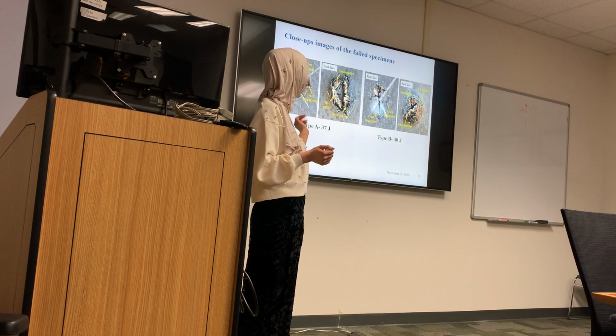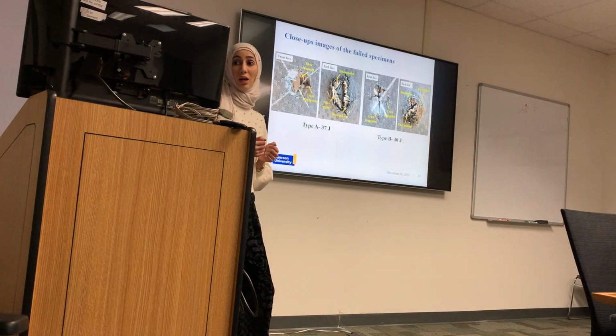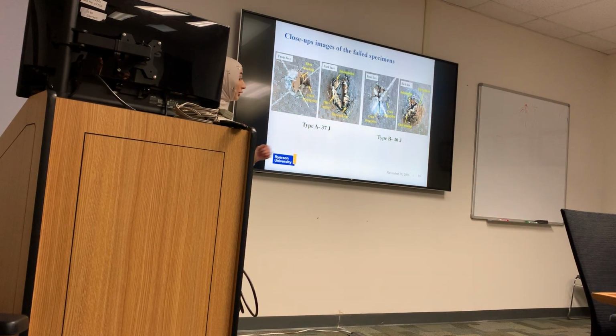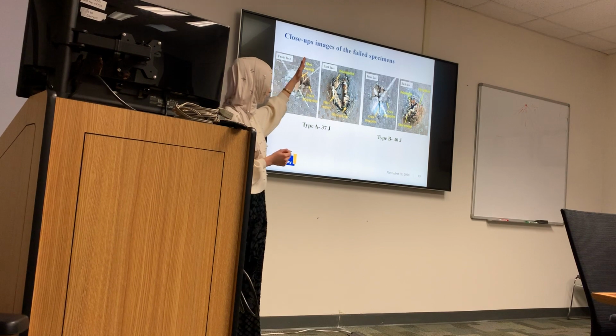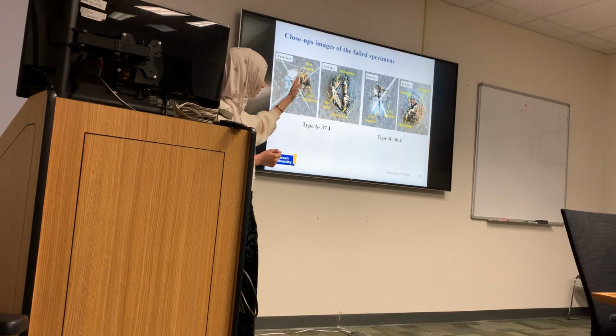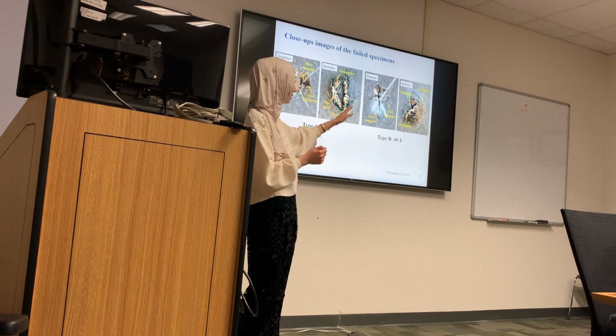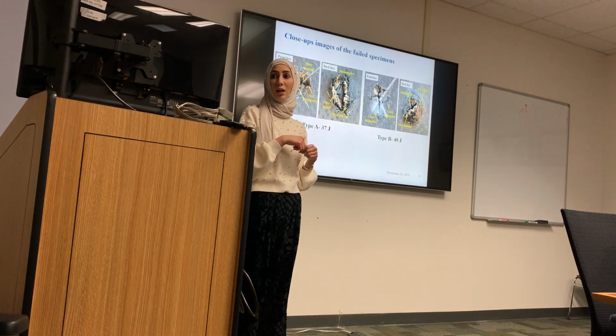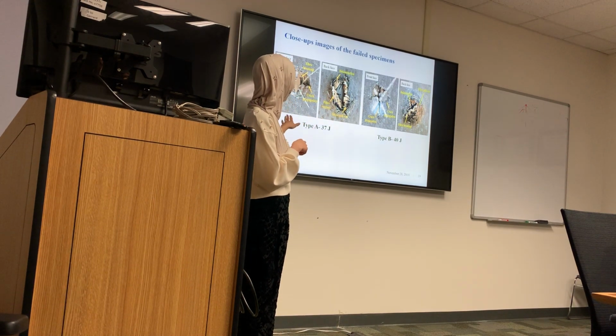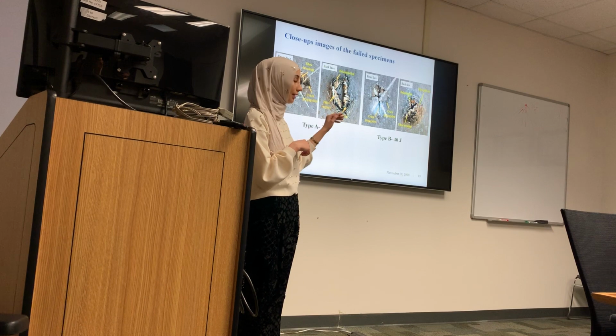where it shows damage like delamination, fiber rupture, and fiber pullout. We also could notice that for unidirectional, the cut is more like a vertical cut, whereas for type B we see more of an X shape. We also can notice that type A created a bigger damage area than type B.